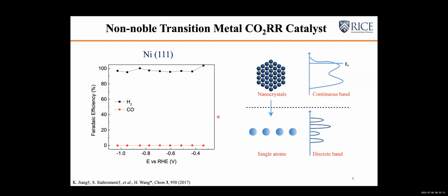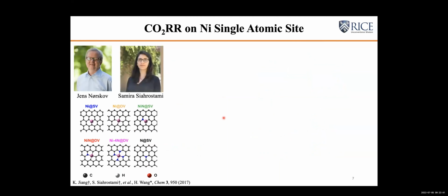By saying single atom catalyst here, we are not referring to floating atoms in the atmosphere or so. We are referring to isolated transition metal atoms that are anchored in some well-defined, let's say, carbon substrate, but there is no direct nickel-nickel interaction. So the spacing between them is very large, so there is no metallic bond formed, so that you can significantly change the electronic properties. We were hoping that by changing the morphology could result in some electronic property change towards more CO2 reduction selectivity.